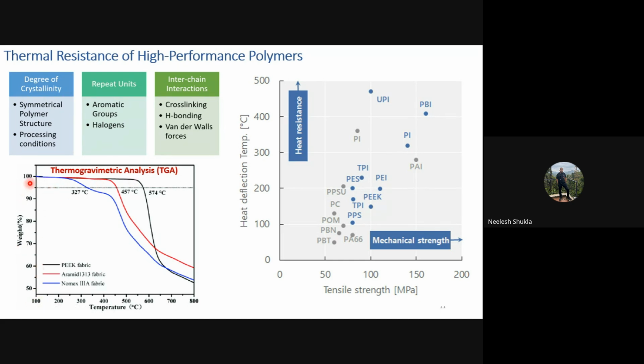Generally, a polymer is taken and subjected to a heating rate from room temperature to a high temperature, and the material goes through Tg, then Tm, and then to further higher temperatures. Most of these polymers are organic polymers, and they would start to degrade at a certain point. At what temperature this degradation takes place depends on their structure again. Generally, polymers which have a higher degree of crystallinity will degrade at a higher temperature. Polymers whose repeat units have aromatic groups and halogens will again have better thermal stability. And obviously, polymers which have cross-linking or some kind of secondary bonds like hydrogen bonding or van der Waals forces will also be more stable as compared to the other polymers. So these factors push the thermal stability of polymers to a higher level.